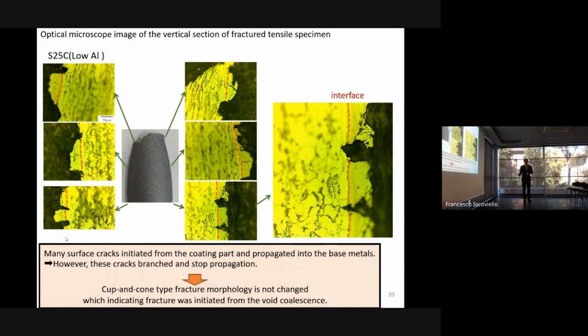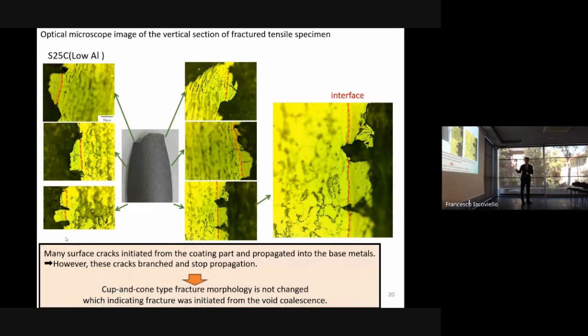So the cup and cone type fracture morphology does not change in the uncharged one, the hydrogen precharged one, and the coated one or uncoated one. Every specimen has a cup and cone type fracture, which indicates the fracture was initiated from void coalescence inside the specimen, not from cracks at the coated part.